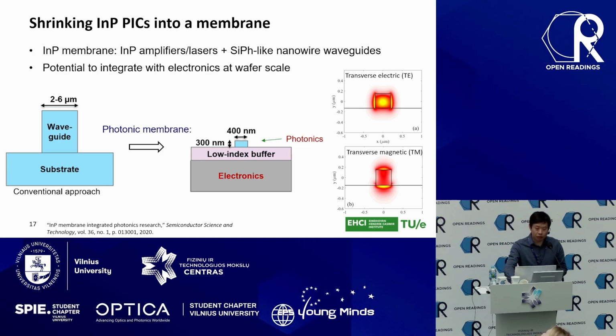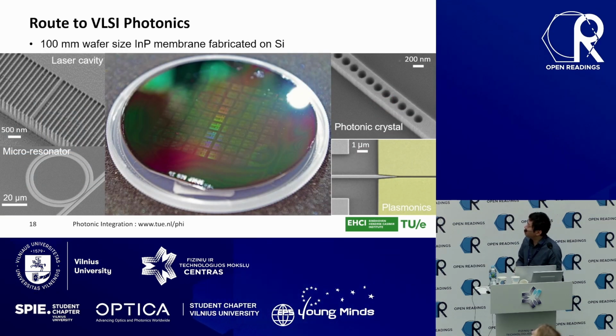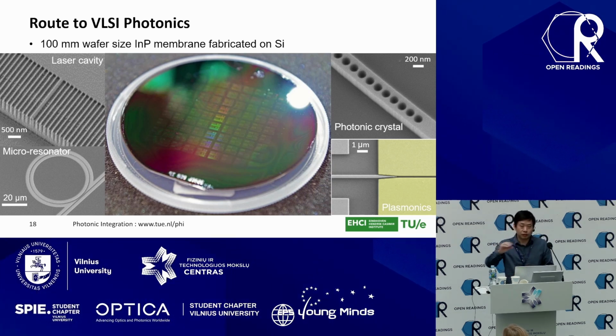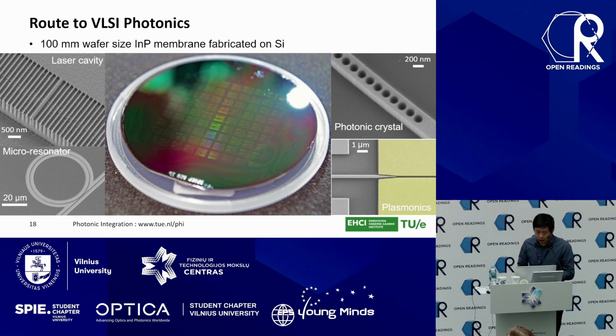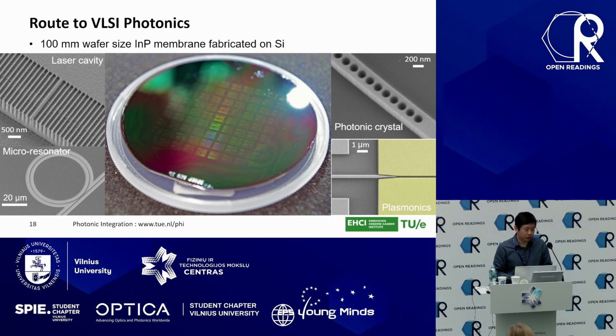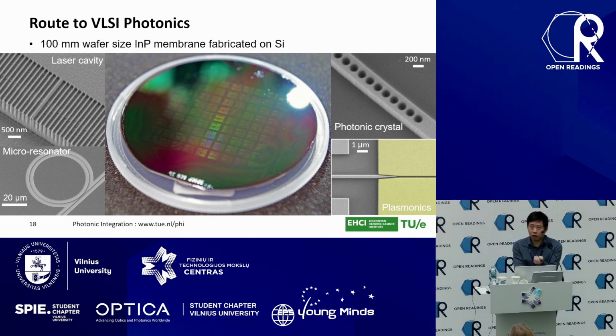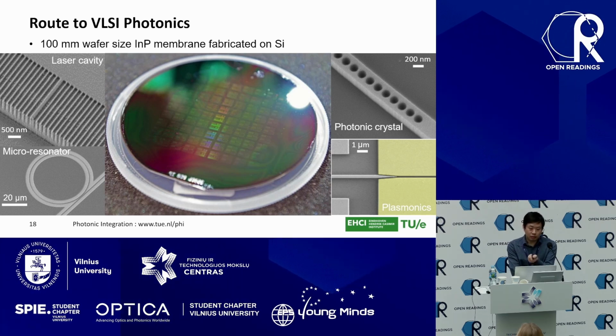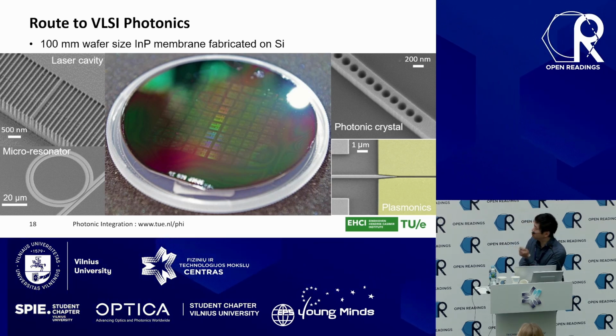So we went on this path, and this is what we have now. We can do in-house fabrication of this indium phosphide membrane integrated on silicon at the wafer scale. We use 100 millimeter wafer size, and on this indium phosphide membrane, we can create laser cavities and all other kinds of nanophotonic devices: micro ring resonators, photonic crystals, and even plasmonics. What you can see here is a coupling region between a plasmonic waveguide and a conventional indium phosphide waveguide.